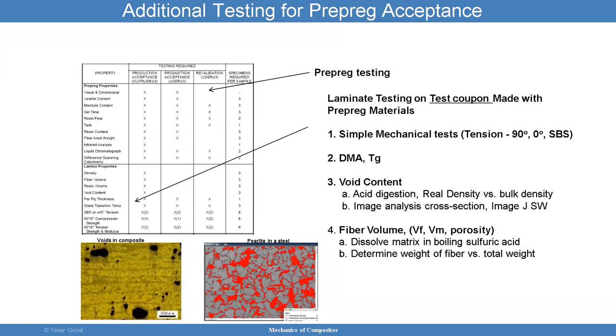The dynamic mechanical analysis provides a lot of information. It can measure, for example, the storage modulus and the glass transition temperature. And it can provide a lot of insights about the degree of cure and the quality of the material. So that's why a DMA is important, and it's typically done anytime you get material in the lab from a different lab. So you bought material, you want to do a DMA.